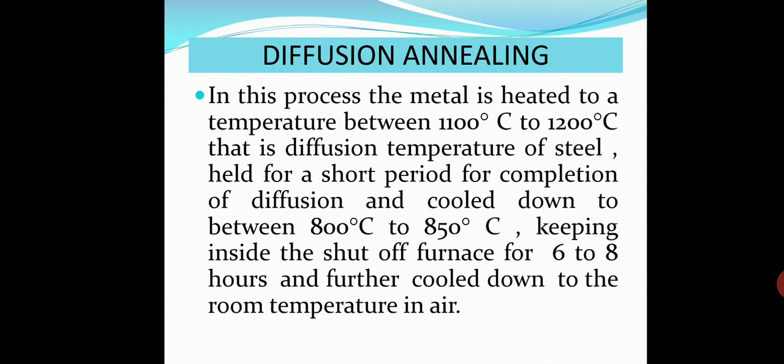In this process, the metal is heated to a temperature between 1100 and 1200 degrees centigrade, a very high temperature. That is the diffusion temperature of steel.